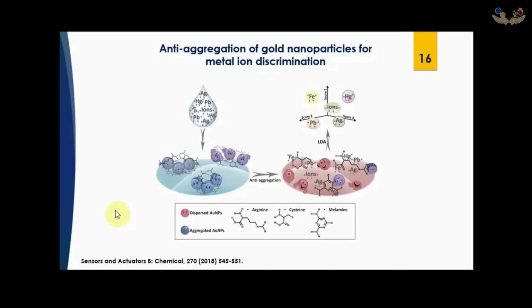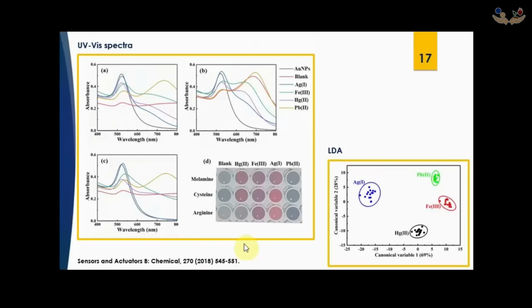The strategy is based on the competitive interaction of citrate-capped gold nanoparticles and heavy metal ions with three aggregation reagents: cysteine, arginine, and melamine. In the presence of aggregation reagent, the color and UV-visible spectra of gold nanoparticles change, indicating the aggregation of gold nanoparticles. Addition of aggregation reagents which are first treated with the ions causes gold nanoparticles to turn from aggregation to dispersion states. The anti-aggregation capability of ions toward various aggregation reagents is different because of distinct stability constants of ion-aggregation reagent complexes.